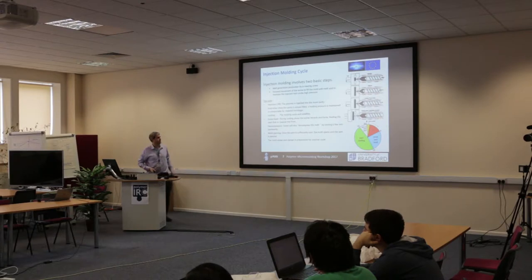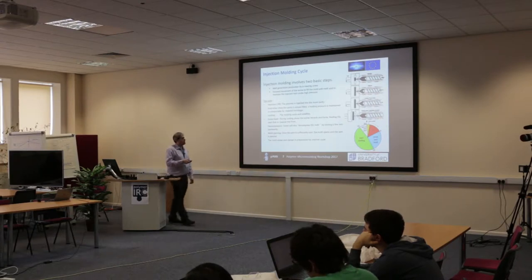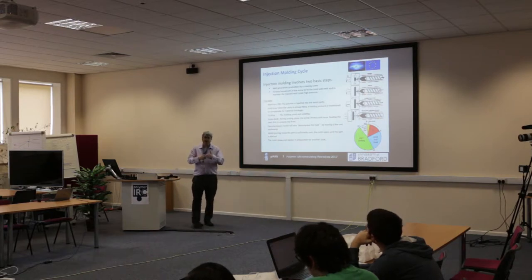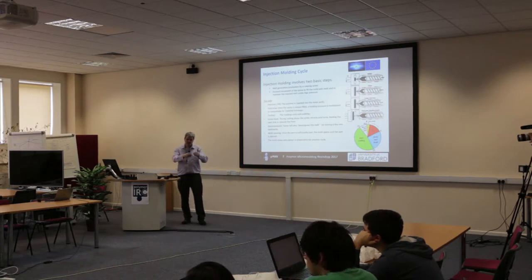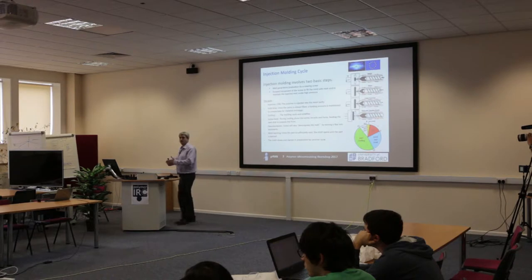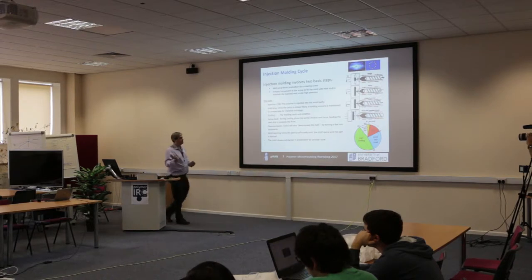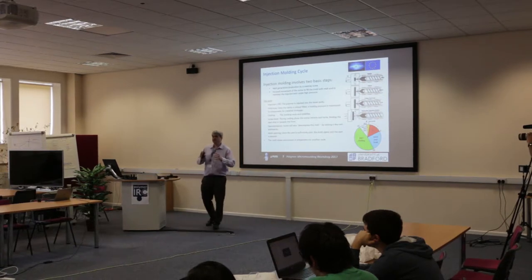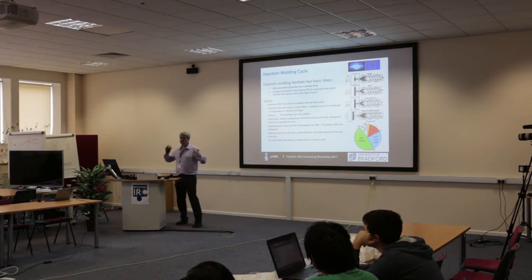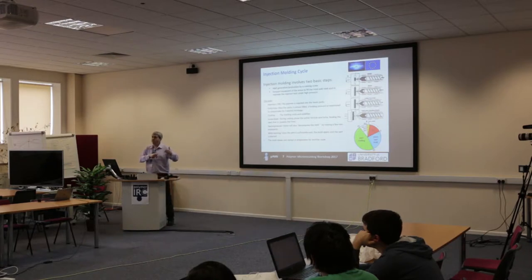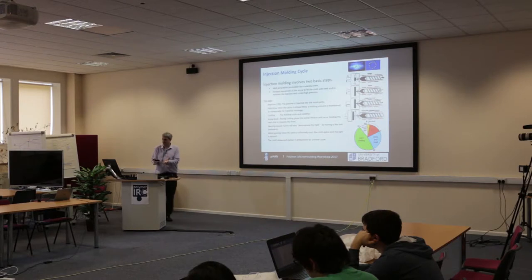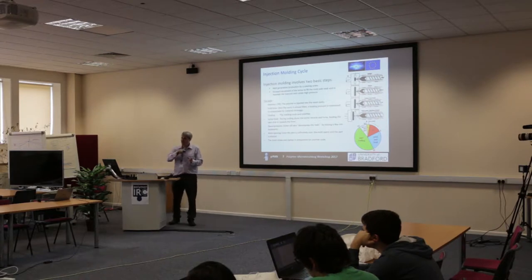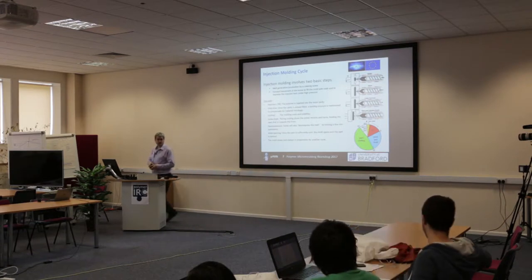Once switched to pressure control we can impose a pressure limit on the filling phase and avoid pressure spikes. We then sustain that pressure for a given period — often quite a few seconds — which counters the fact that as the material cools and solidifies, its volume changes; it becomes more dense and effectively shrinks inside the mold cavity. By sustaining pressure after the part has filled, we squeeze in a little more material to fill the volume lost by the part solidifying.